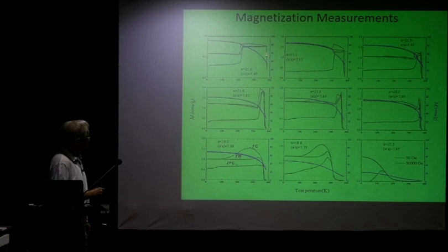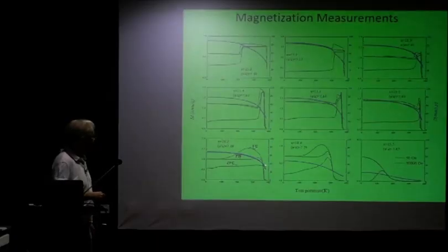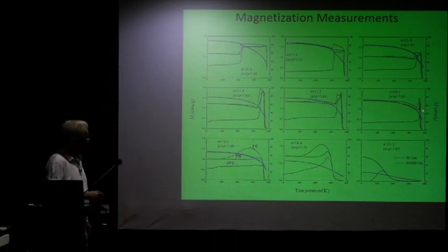So what is happening? This is the Austenite-Curie temperature, right? This steep one over here. And the steep one eventually gives way to the Martensite state, so that the steep one is no longer there. And then we have this part coming in at a slightly higher composition of manganese. And we have now here a Curie temperature that is in the Martensite state, in the L10 state. So these have a cubic to Martensite transition, which you can see in that temperature range, but here you cannot see that anymore.